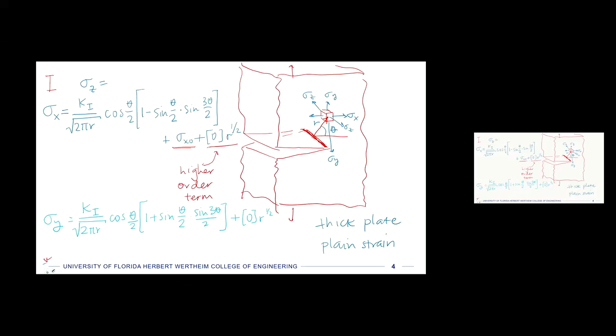So these stresses are related. And then we also have, in this case, a tau xy. So that's going to be, if we have our cube here, tau xy will go across the top this way, and then up and down the sides like this. It'll be on the bottom, and then on this side as well. Just because of where the load is applied, and you can see that as we open that mode 1 crack, we will have a little bit of an angular sort of opening, and so that's where that tau xy comes in. It's a combination of those effects.